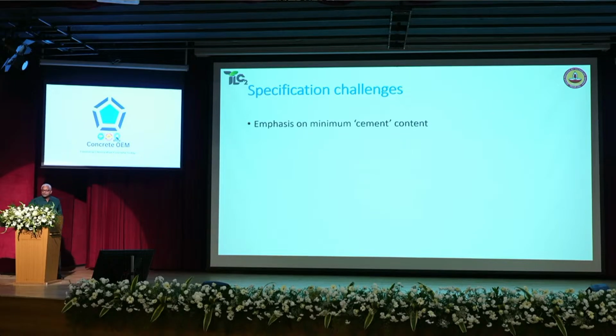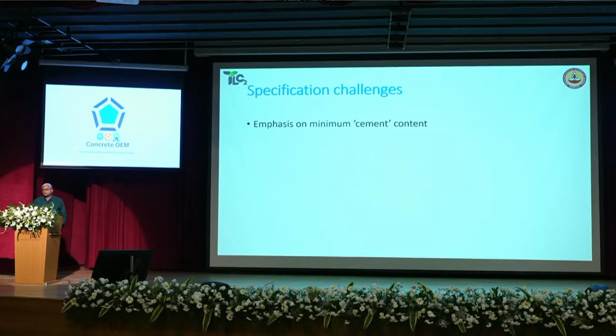There is always an emphasis on minimum cement content in the specifications, right? Now, if you even look at IS 456, many people don't seem to interpret this well. When they talk about the minimum cement content required for durability in different environments, it clearly says at the bottom of the table that it's inclusive of all the additions, right? When I say 360 kilograms cement in an extreme environment is needed, it is inclusive of fly ash or slag or silica fume or any of the permitted additives as per IS 456. Unfortunately, not many people pay attention to that. They still say minimum cement content.